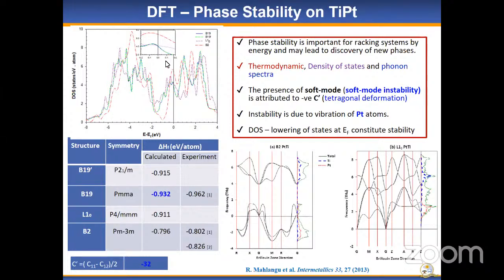And then what we do, we use the relationship between the densities of states on the far top left corner there. And then we look at how the densities of states are comparable for different phases. In this case, I'm looking at 4 phases, B2, L10, B19, and B19 prime. So what one does is to check the behavior at the Fermi level and how the states are actually shifting around this. So now the most important thing is to know that the lowest states at the Fermi level correspond to the most stable system, while the highest is the least stable system. In this case, the B2 will be the least stable.